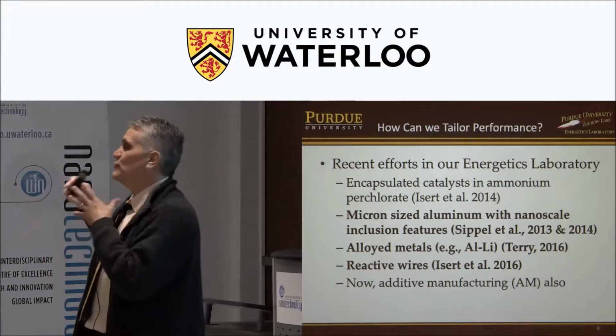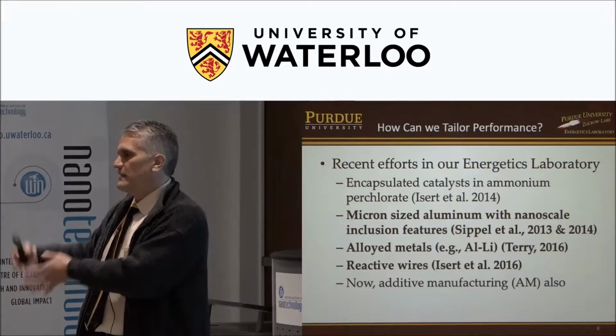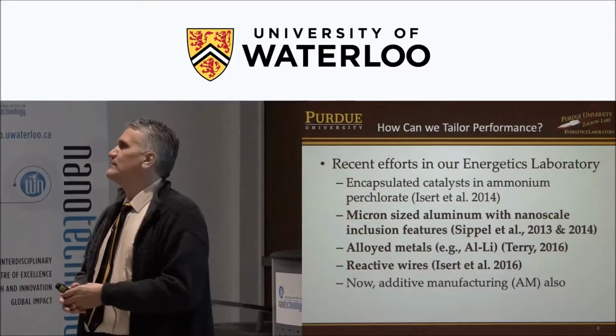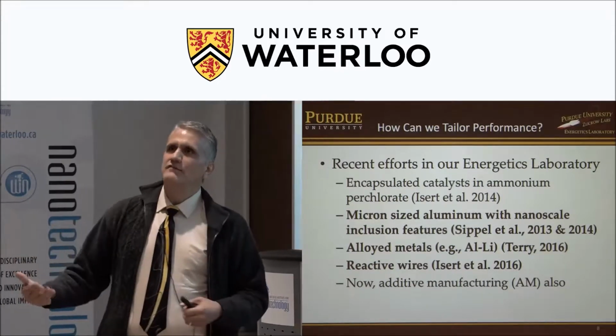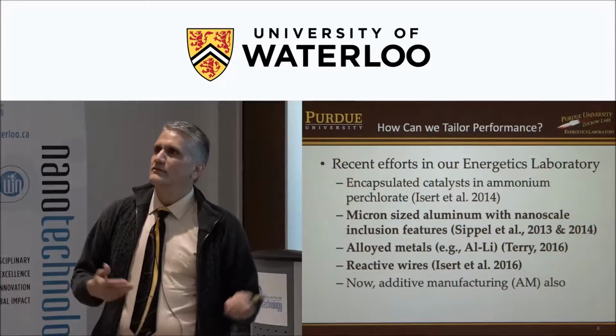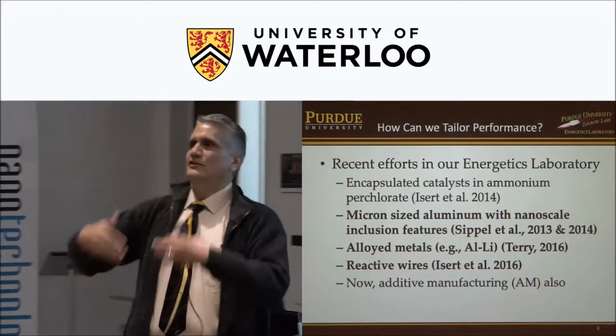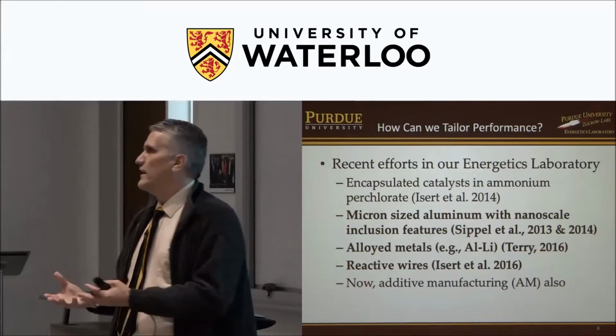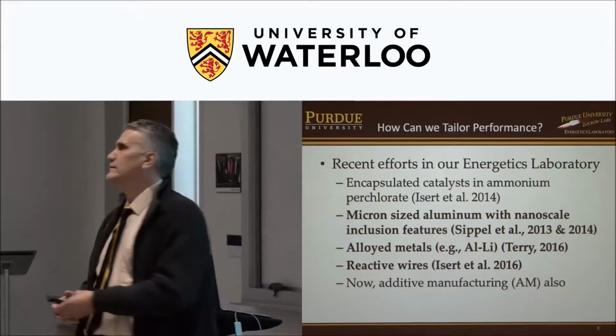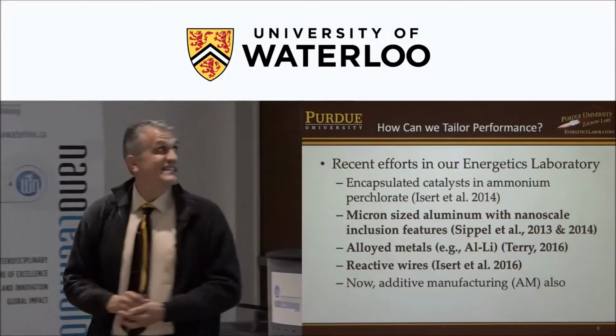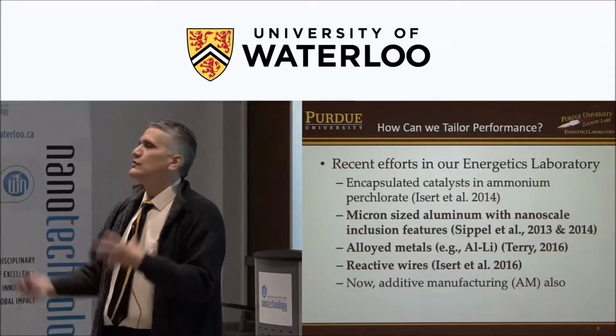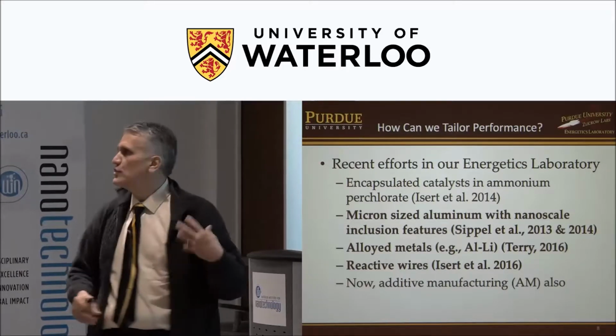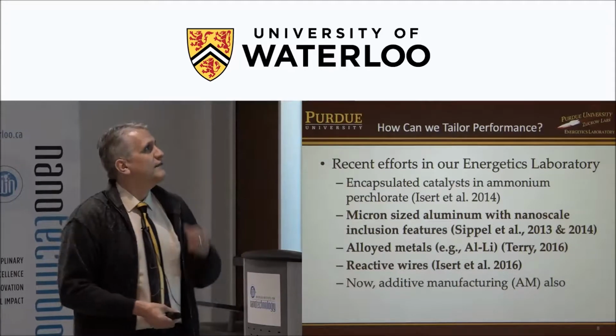The catalyst, if you just mix it in, what is traditionally done, into the binder system, it catalyzes the aging of the polymer. So there's some material scientists in here. You know that polymers degrade with time. So your solid propellant can degrade with time as those catalysts accelerate that aging. You don't want that. So it's better to put it inside the crystals. We showed that it's more effective in catalyzing the burning.